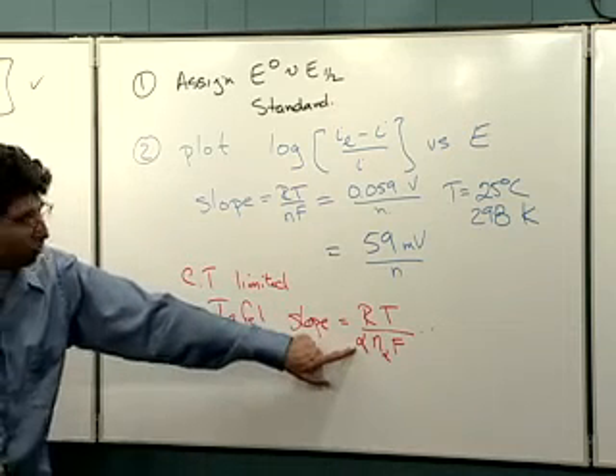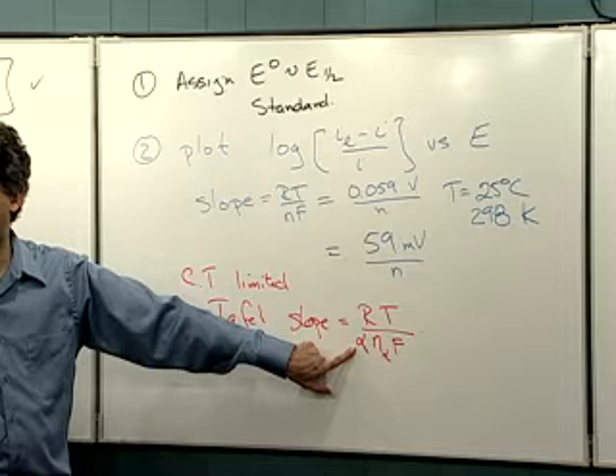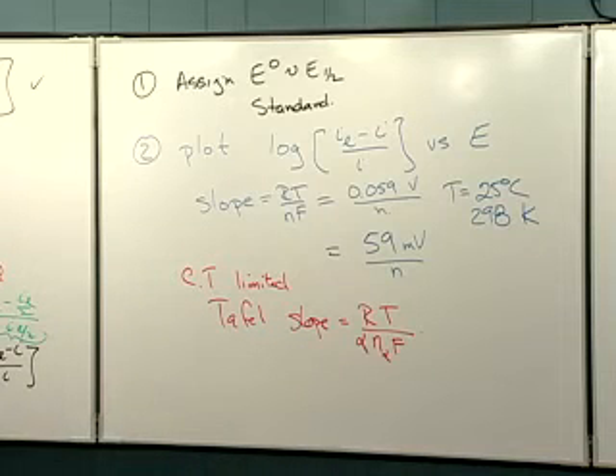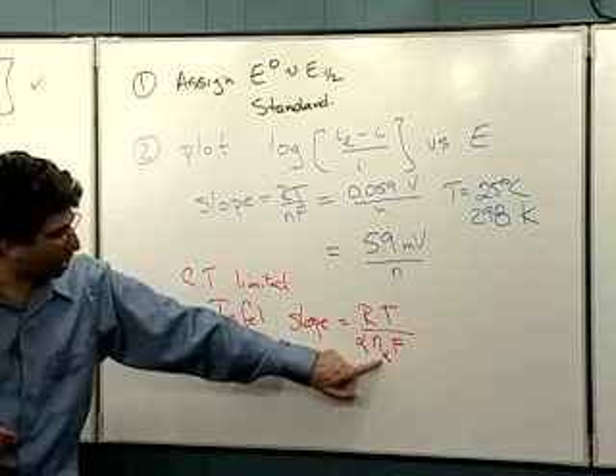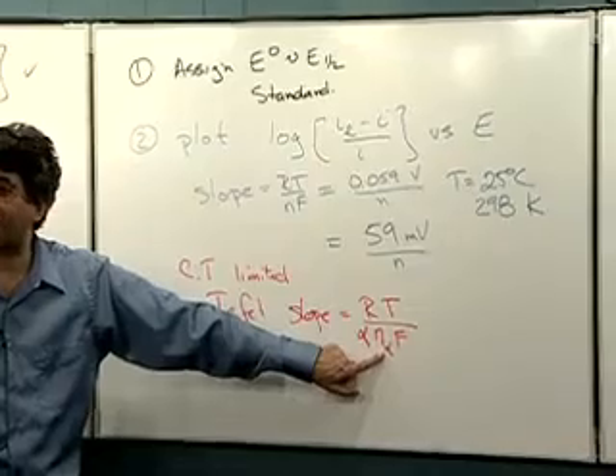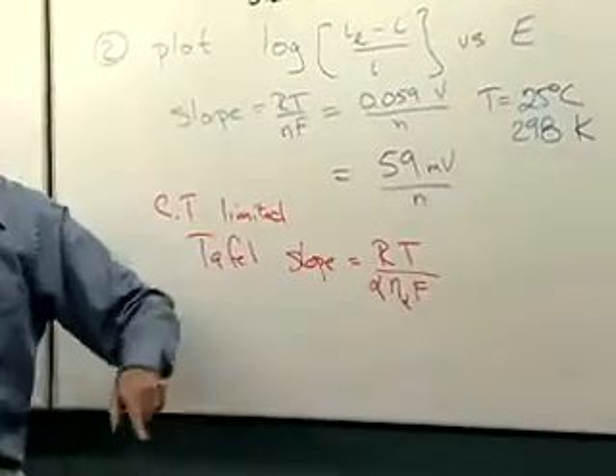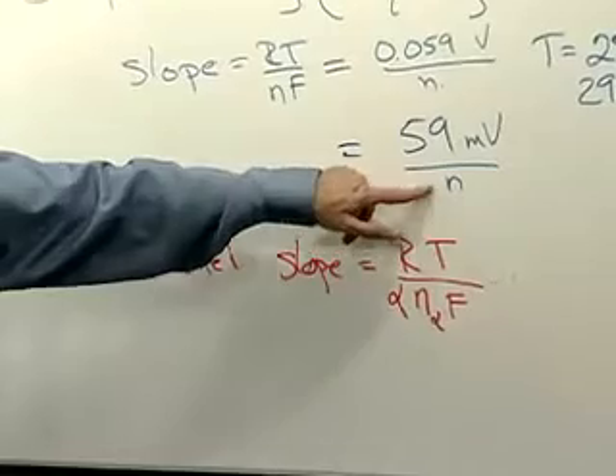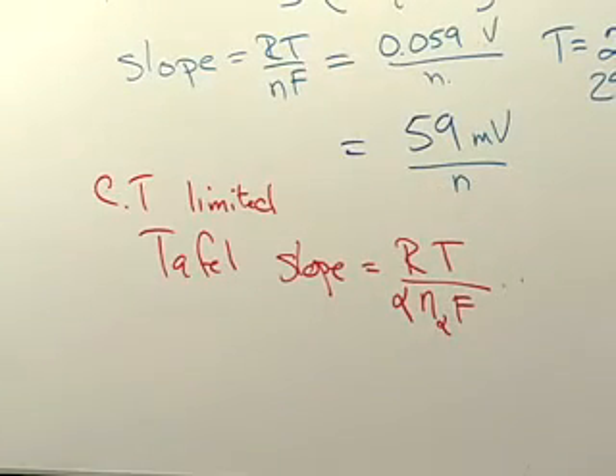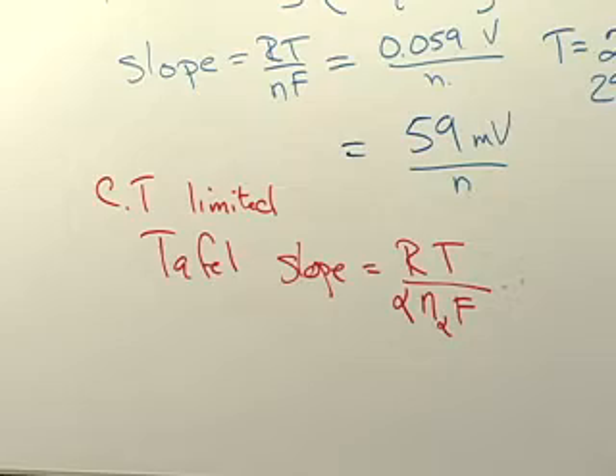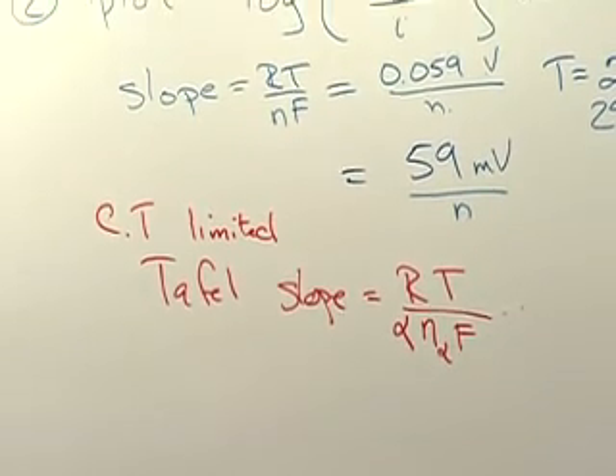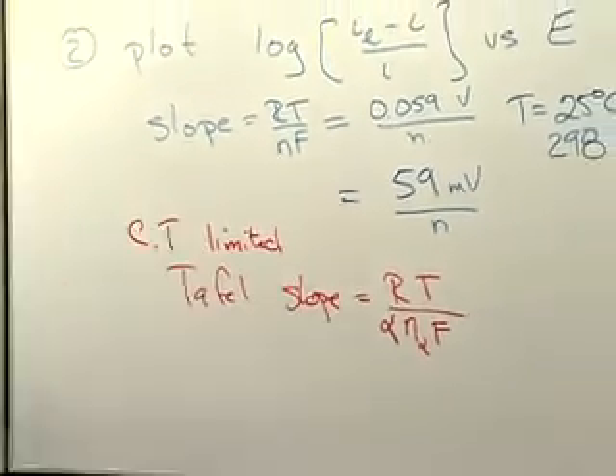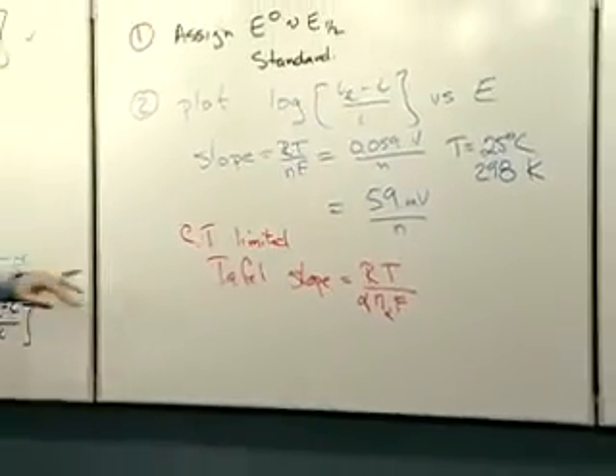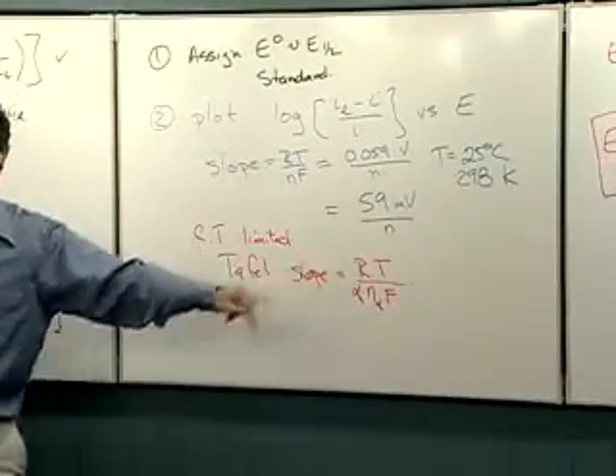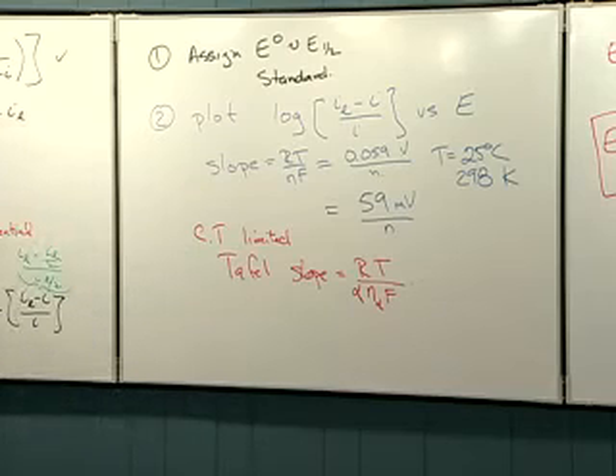First of all, it'll differ by this term alpha, which is the symmetry of the barrier. But remember, that's probably 0.5. And second of all, and that's why I put the alpha down there, it will be affected by this number n. So you can see, in the case of direct ethanol, taking that as an example, if I am mass transport limited, then n equals 12, the stoichiometric value over here. If I am charge transfer limited, then n is either going to be 1 or 2, depending on exactly what the mechanism is. And so that makes a huge difference in this slope. Which probably was the problem. There's the solution to the problem.